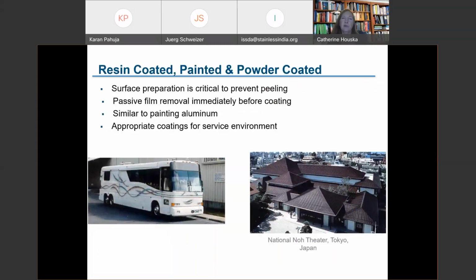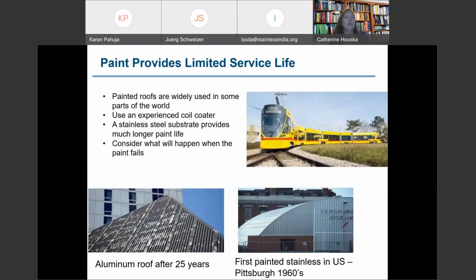Paint is applied to stainless steel. It's more common than many people realize. Stainless steel buses are very common around the world, and usually you don't see the stainless steel. They're usually painted. In Japan, a fairly large percentage of the roofs are stainless steel, but they paint them. So it's not hard to paint stainless steel, but it is like painting aluminum in that you have to make sure the passive film is removed immediately before the paint system is applied, or at least the primer is applied. Otherwise, the paint can peel off. Painted roofs are pretty common in addition to transit. This is a stainless steel train that's painted.